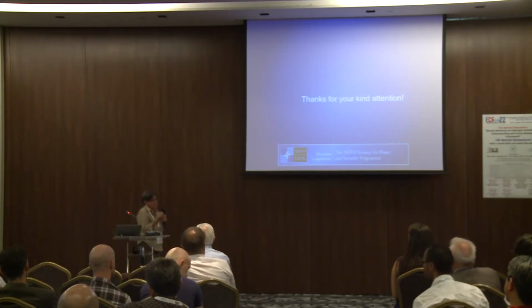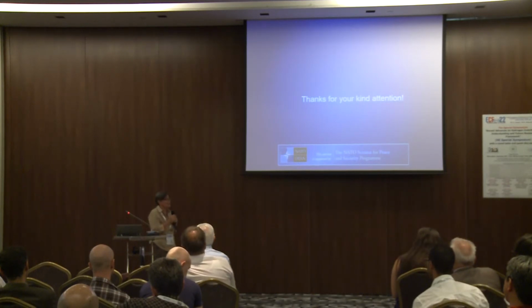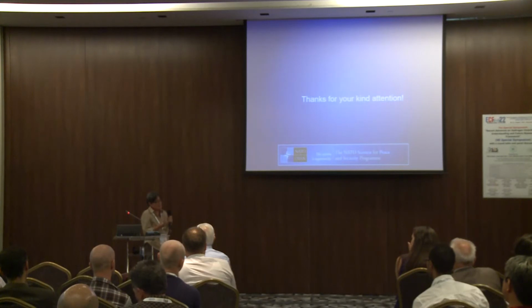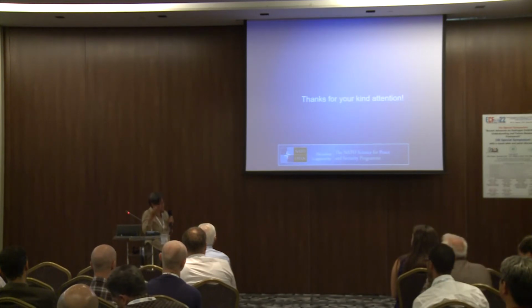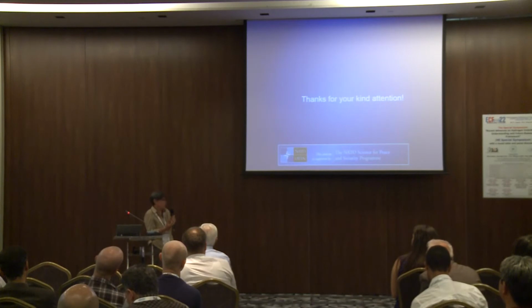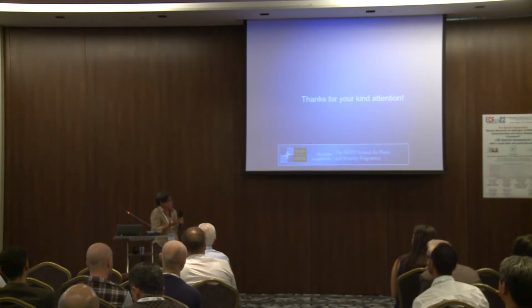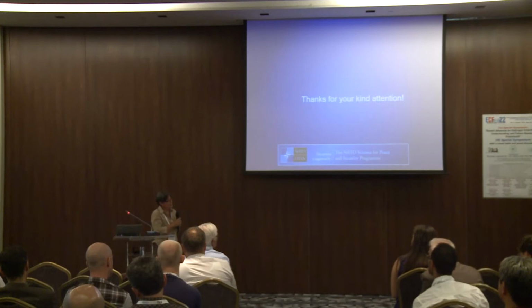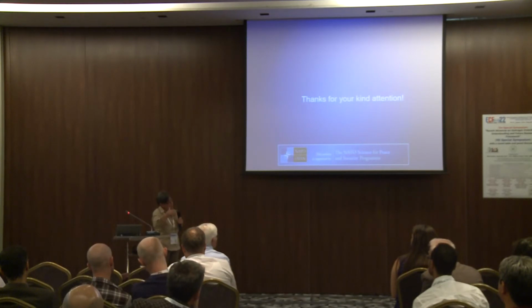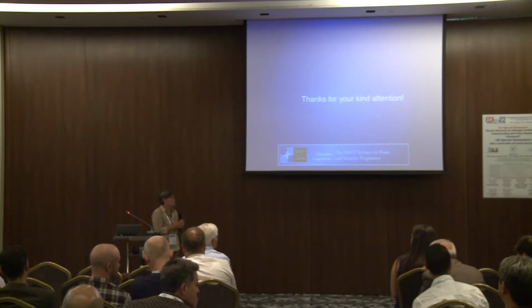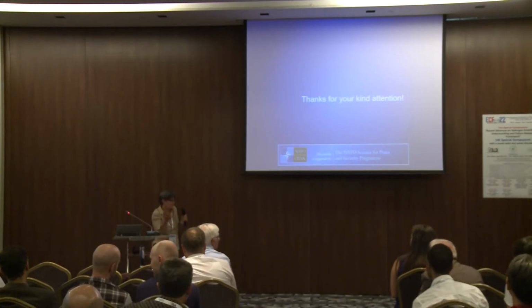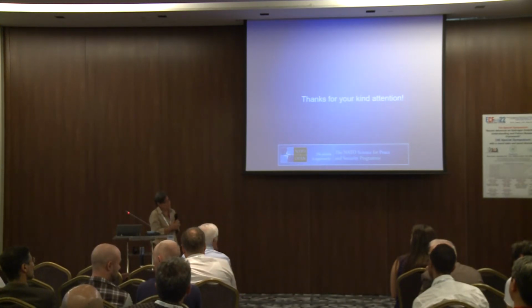So the basic idea here is that, as Giovanna Gabetta was saying, sometimes you just have the feeling that something is going wrong. And in this case, you can simply take samples and then perform more sophisticated investigation, which is the only way to sort out what is the origin of that. But before going there and taking the sample, these sorts of techniques can help you say the material properties are more or less stable, or the material properties are going to change with time, at some rate, and therefore decide when it is the time either to replace the material if something is going wrong very fast, or to make a deeper investigation to understand what is the reason for that.